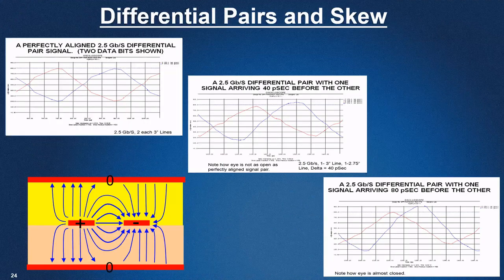So a little bit more on skew. You can see in the lower left a diagram of what a differential pair would look like. And ideally, the upper left is what you would see in terms of the propagation speed between the two signals. And then you can see as skew gets worse, you see a shift in the speed, and then you end up with a delay in picoseconds. And obviously, if it gets to a certain point, the system won't work properly. So again, using spread glass will make the decay effect more uniform, and you'll have uniform signal propagation between the two traces.